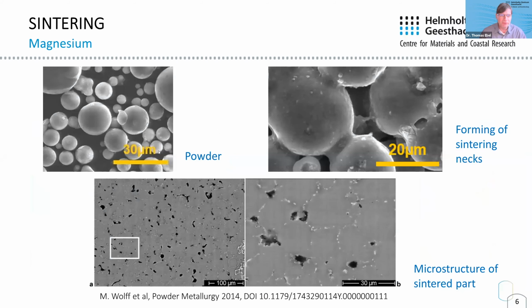Nevertheless, if you have this experience, then the powder can sinter very nicely, and you see here the pictures which are quite similar to the titanium ones. There's one difference, and that's these oxides. As I said before, you can see them in the microstructure, in the material, and in principle it's the surface of the former particles.